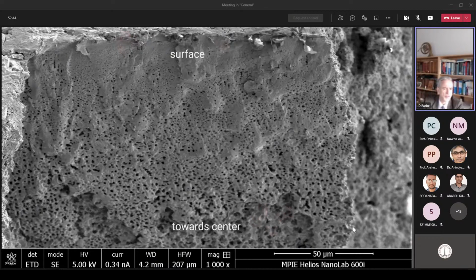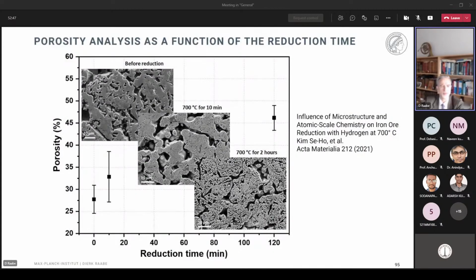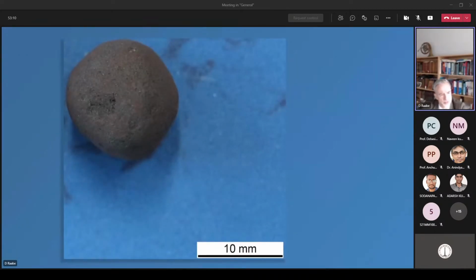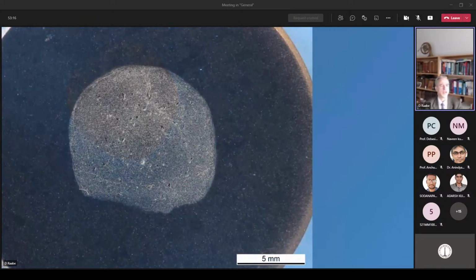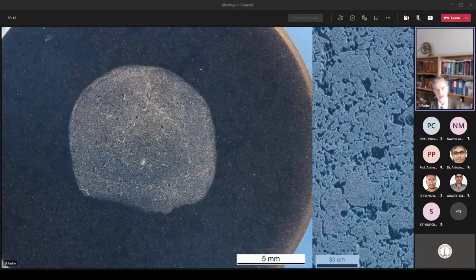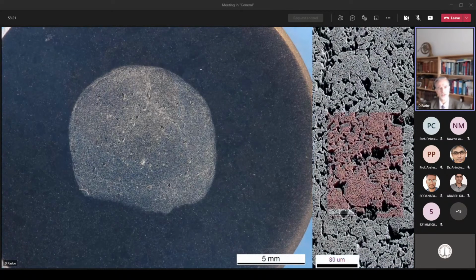While in the center, the porosity is leading, and the phase transformation volume change is leading to massive stresses and to diffusional pore build up. Now the porosity during that reduction step in a Midrex type hydrogen-based process, as you see here, can at the end of the process occupy between 40 and 50% of the entire pellet volume, while the inherent porosity was maybe about between 25 and 30%. So you have a massive increase of the porosity. Here's such a pellet, and we try to do some theory and bottleneck theory and full field calculation on this.